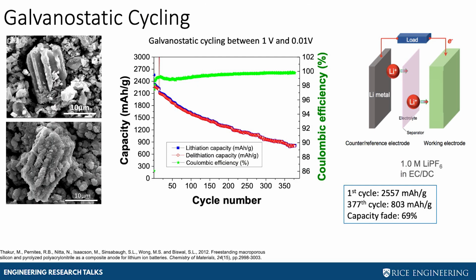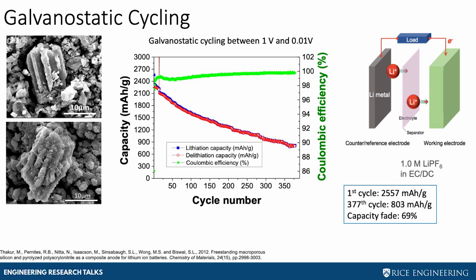When we first started cycling this, here's a picture before we start cycling and after we've cycled a couple hundred cycles. The capacity is actually quite high. Remember, I told you graphite is somewhere around 400, a little bit less than 400 milliamp hours per gram. So our silicon is up here at 2400. But notice there's a big fade that happens. Over these 300 cycles, we saw a loss of about 70% in its capacity.